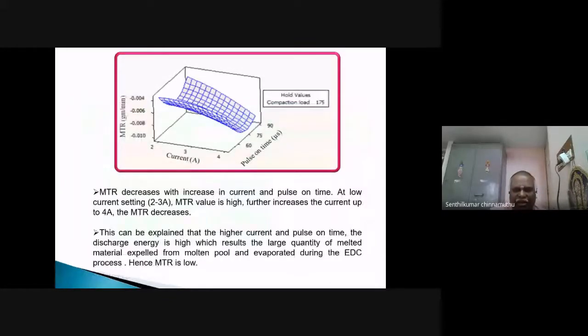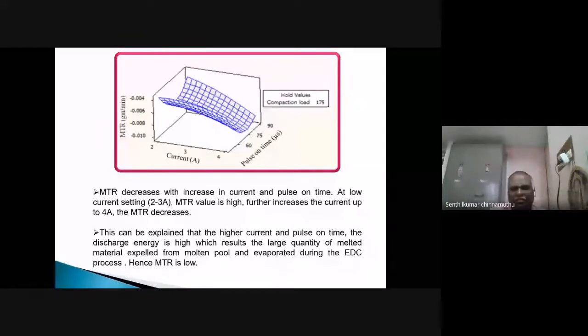See, the effect of current and pulse on time on metal transfer rate. The metal transfer rate decreases with increase in current and pulse on time. At lower settings, the metal transfer rate is higher, MTR is high. With further increase in current up to 4 amps, the material transfer rate decreases. This can be explained by the higher pulse on time and current, the discharge energy is higher, which melts more amount of material and evacuates the molten pool, and it is evaporated during the EDC process. Hence, MTR is low. Conversely, metal erosion takes place. That is, metal removal takes place.